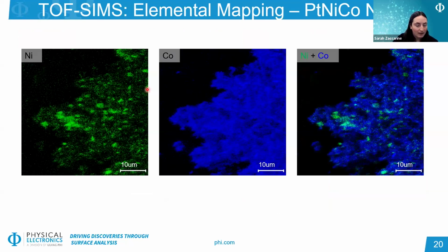And in this sample set, we also imaged the nickel and cobalt and collected these elemental maps. We see again that the cobalt is present in clear amounts throughout all of the nanowire features. You can see some of those nanowire structures quite clearly. With the nickel, however, this is not really looking like the nanowire shape. It's more clumpy. It's kind of segregated in certain regions.